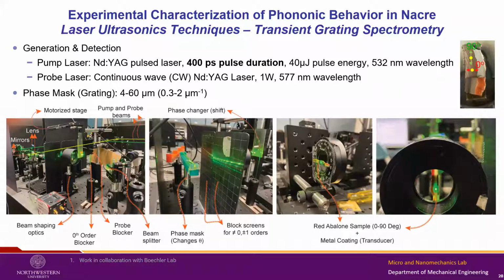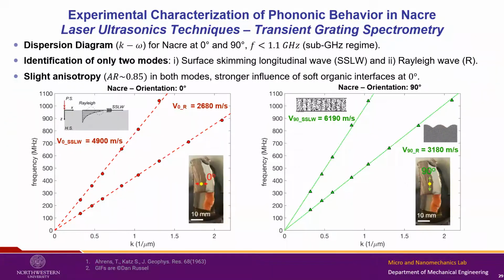And for that, we're using a technique called transient grating spectrometry, where basically what we do is we cross two lasers on the surface of a material, and these two lasers create a transient grating, which is basically a transient temperature profile, which generates expansion and contraction of the material, and that launches acoustic waves through it. And then with a probe laser, we are able to pick up that signal. This kind of technique is limited in terms of the frequency that you can study, so up to like 1.1 gigahertz. And so far, that's what we have been studying.